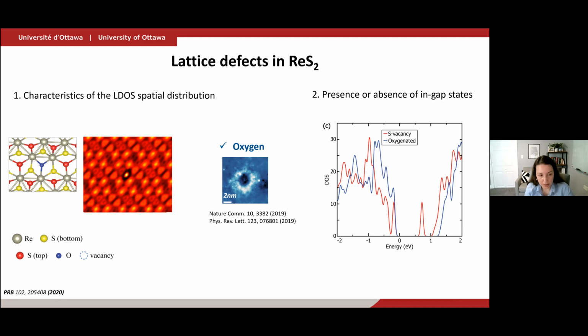So why are these atomic scale defects of interest? For several reasons. They can affect, for example, the excitons in these 2D materials. They can affect catalysis in these 2D materials. But also importantly, they were found to give rise to single photon emitters. And so although people measure them as single photon emitters on the surface, so far there is very little information as to correlating the precise nature of the defect, their location, and the single photon emitting phenomena.